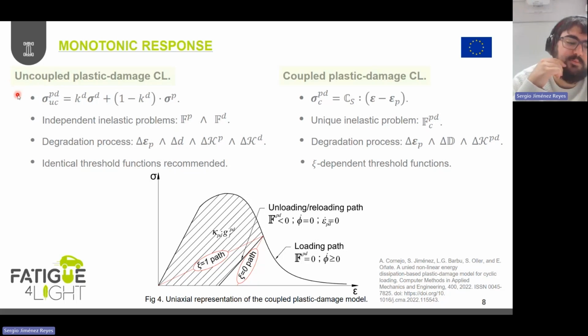This model is based on the rule of mixtures, but we adopt here another point of view for this rule of mixtures law, where instead of mixing the response of two different materials, what we're mixing here are different constitutive behaviors. In particular, we are mixing damage behavior and plasticity behavior. So by mixing them, we obtain finally the material response, this plastic damage material response. And the main particularity of this constitutive law is that it uses independent yield criteria for the plastic and the damage responses being controlled in the material. And then, of course, the degradation process in this case is being characterized by the accumulation of plastic strains combined now with the accumulation of damage and the evolution of the strength of the material.